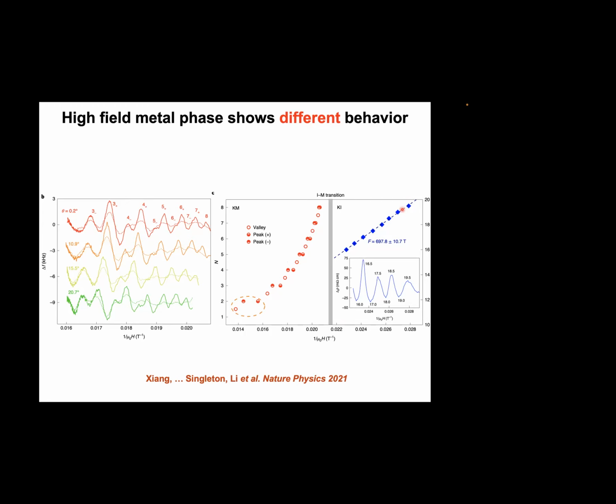Let me quickly do this contrast. At low fields, it is an insulator, transport-wise. And yet, resistivity shows the oscillation and follows an exact linear trend in this Landau level fan dependence, right? Here in strong field, it's a metal, but when we look at a Landau fan, it's strongly nonlinear. A metal shows a very strange nonlinear pattern, whereas an insulator shows just a straight line. Again, that's a big contrast, and seems to suggest that whatever happens inside this sample is very different from what happens in the metallic states.